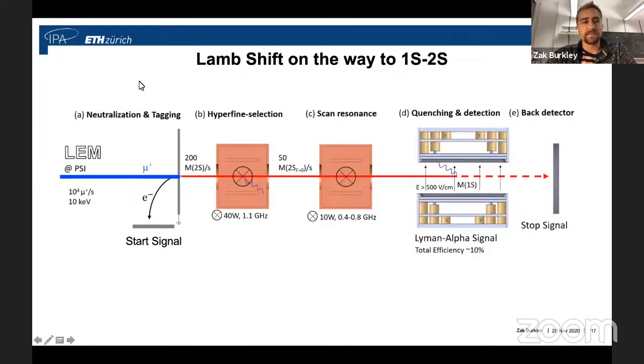So how we plan to do the lamb shift measurement is we'll take the muon beam line from PSI, where we have about 10,000 muons per second. They'll hit this carbon foil, and we can get, I'll show you the results here that show this, about 200 muoniums in the 2S state per second. And then to do the lamb shift measurement, we're going to depopulate the 2S state by mixing it with the 2P state, and we'll look for this lack of 2S atoms, meaning that we successfully drove the transition from the 2S to 2P.